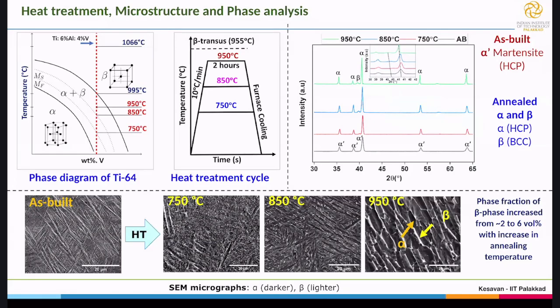Imagine inside the 3D printer, the component will undergo an extremely high cooling rate. The cooling rate is about 1 million per second, almost 10 to the power of 6 Kelvin per second. That very high cooling rate leads to the formation of a non-equilibrium microstructure, as you're seeing here in the as-built structure, which is alpha prime martensite. It does not give the desirable properties, so I cannot use it for the purpose I'm thinking of.